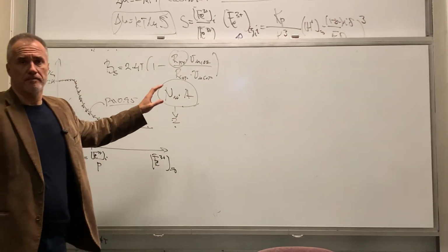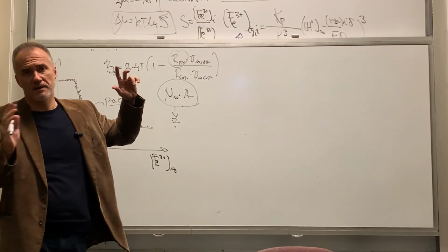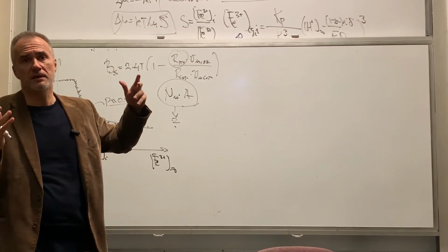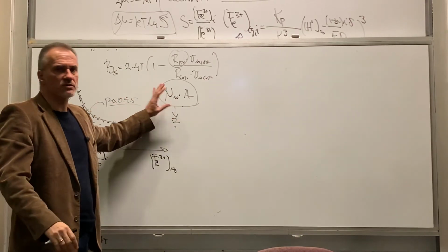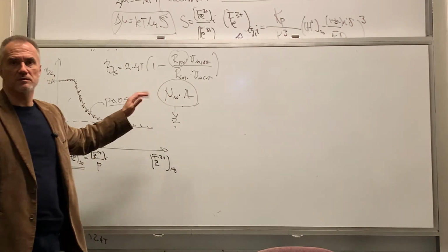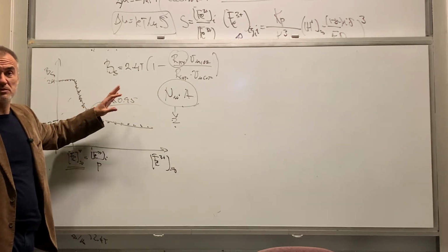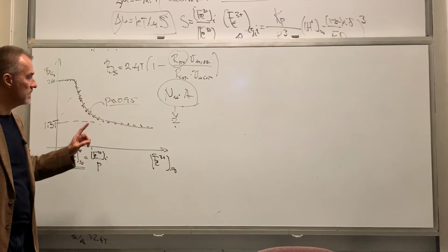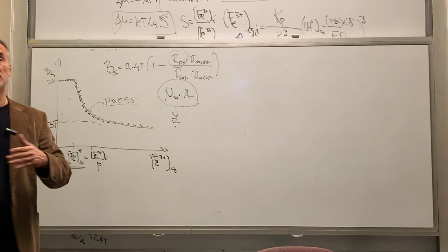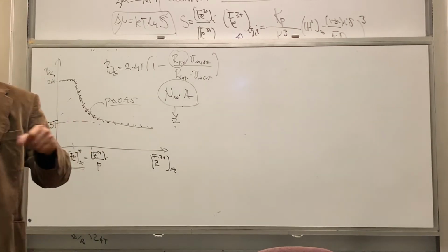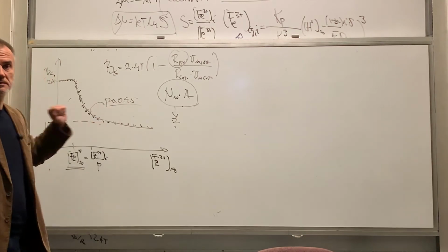By the way, it has a physical meaning, and it gives you an idea how big average nuclei could be, but I'm not going to go into this because they're very small. But the bottom line is that P is very close to 1. So you almost would not make a big mistake assuming that P is equal to 1. Almost no depletion of iron 3 at the interface. But let's keep it as it is, so you understand.